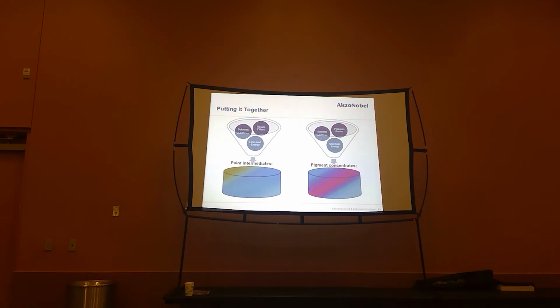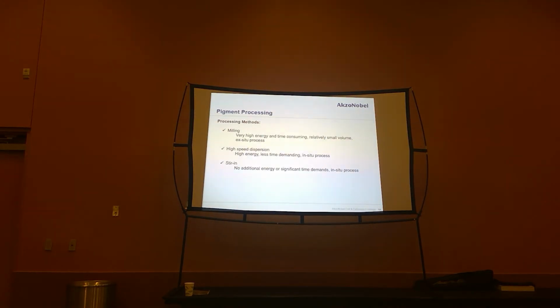So again, like the paint intermediates, we have pigment concentrates that include mainly pigments, some resins, some solvents and additives. But the important point here is the medium to high energy versus the low to medium energy for the paint intermediates. This is where the skill, the time, the effort really goes into paint manufacturing to get these particles finely dispersed. So we're going to talk about this for a minute, because you've got to know what you're doing. There are special techniques to do this, and if you don't properly disperse your pigments, you will have problems.